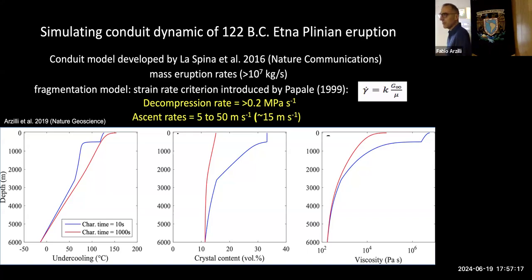So basically we reach a threshold during fast magma ascent, and fast magma ascent means that the ascent rate increased from 5 meters per second to 15 meters per second. In the last part, when you reach 10 to the 6 Pascal second, basaltic magma can fragment, feeding highly explosive eruption. In this case, instead, the red curve shows a very small amount of crystallization during ascent, because equilibrium is approached slowly. You have an increase of viscosity, yes, but not too much, and the magma will reach the surface, but possibly feeding fountaining eruption.